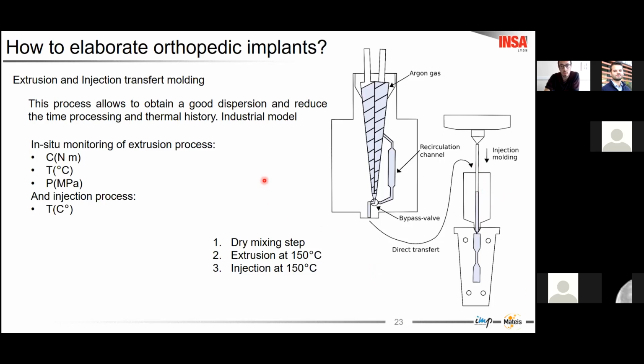This elaboration protocol allows us to reduce the residence time at high temperature and reduce the degradation by hydrolysis, simulating an industrialization process and obtaining composites with good dispersion.